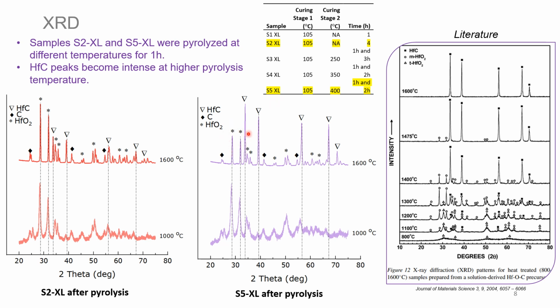This result corresponds well to the data from the literature, where you can see that with the increasing temperature of pyrolysis, the intensity of hafnium carbide crystals also increased.